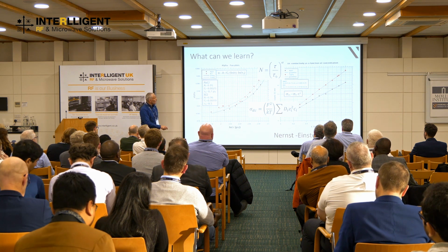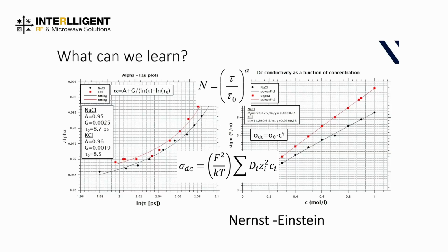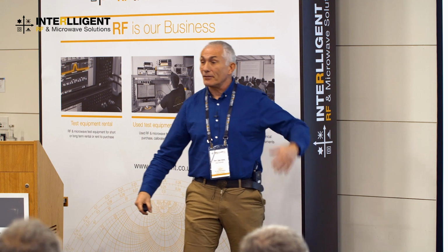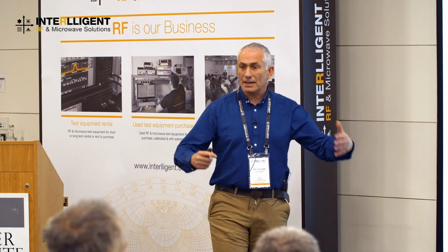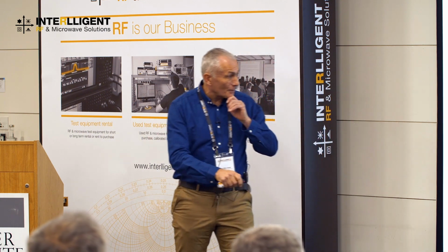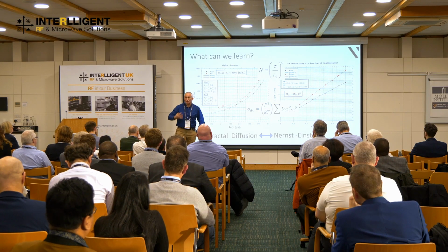Now, that's lovely, but it doesn't work. As you can see, I don't get a linear relationship here. I get a power law when I actually do the work and plot it. Very unusual. I get a power law. Well, that's self-diffusion, how we would like nature to behave. However, nature does not behave that way. A power law is a badly behaved 5-year-old child, and so we actually need what's called fractal diffusion. We have to once again take into consideration the fact that there are motions, there are times to wait, etc., a continuous random walker. And that's something quite new. People didn't actually realize that. That's going to be published very, very soon. So there you go. That's what you can do with gigahertz spectroscopy.